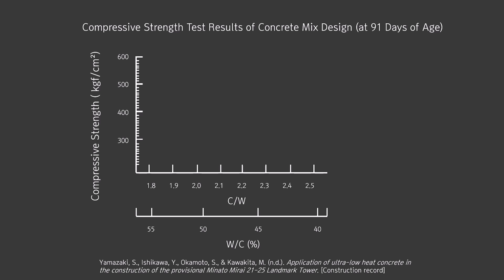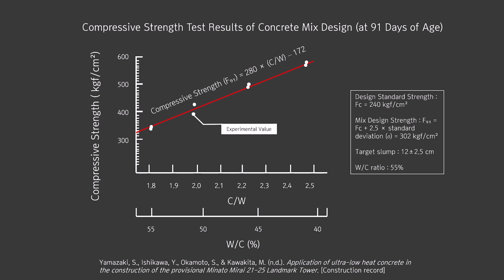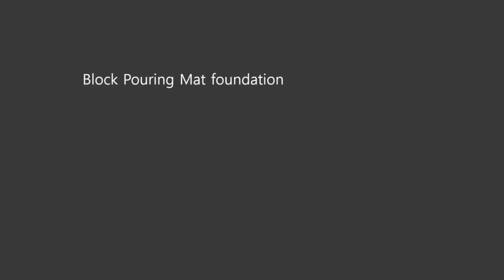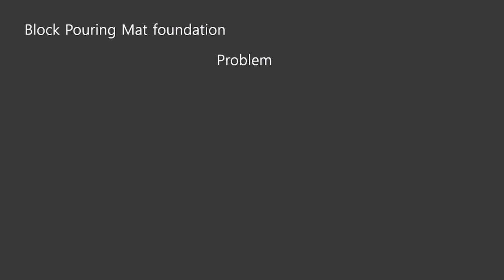Slump and strength control were also critical. They aimed for a 12 plus or minus 2.5 cm slump and 240 kgf per square centimeter design strength. The actual mixed strength was 302 kgf per square centimeter with a 55% water-cement ratio. But one question remained: how did they pour so much concrete at once, given the old pumping tech? In most large buildings, mat foundations are poured in segments, but not here.